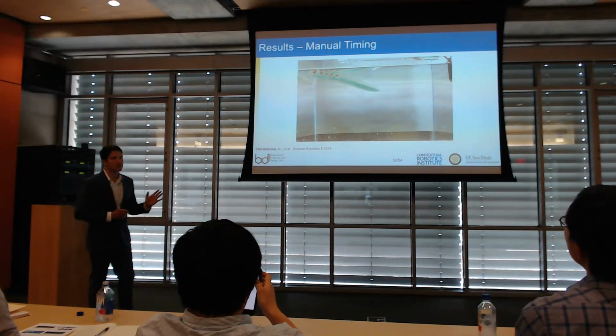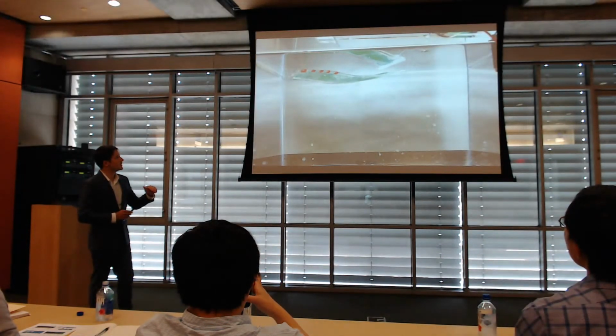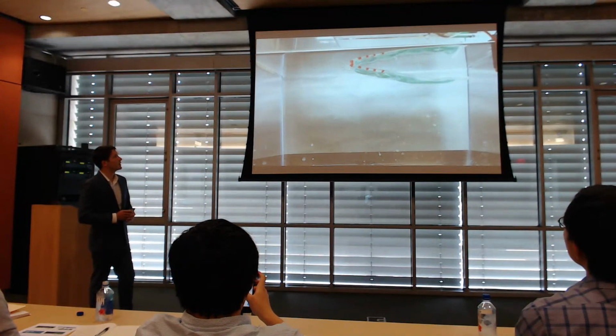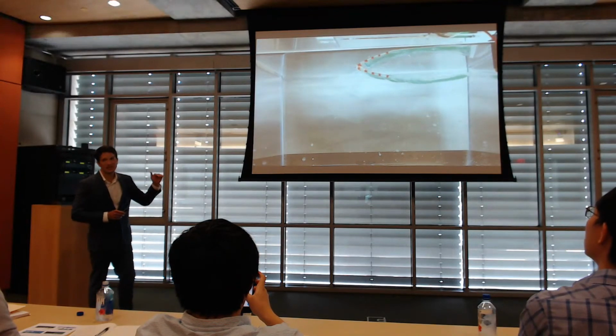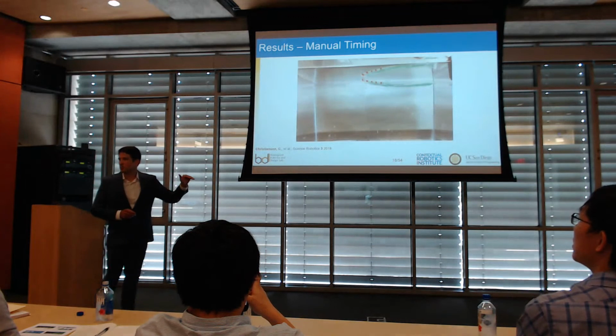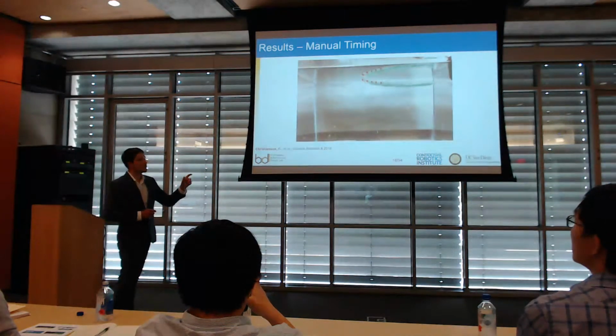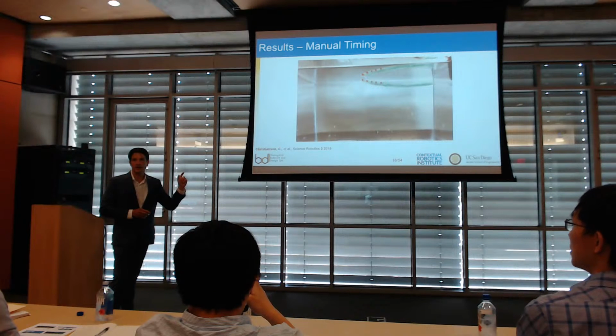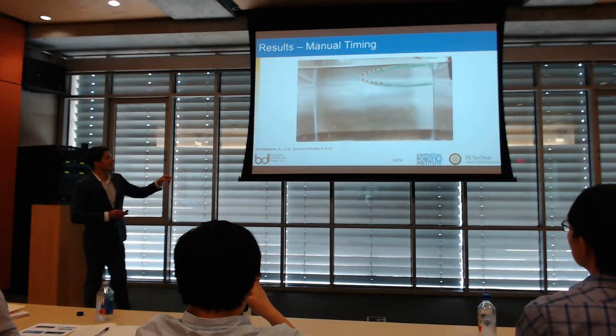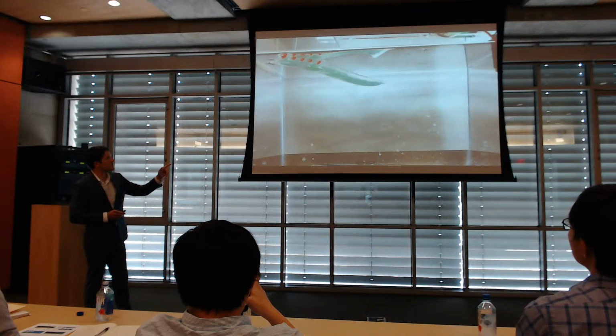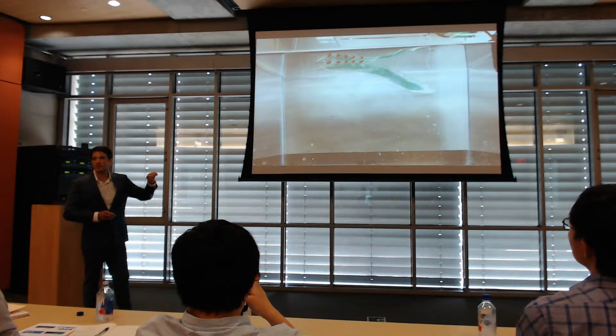Then we also wanted to see if we could get this to swim through the water. This is tethered swimming, just a single bimorph actuator. I'm applying voltage to both sides of the actuator to get it to wiggle its way through the water. The trouble with this one is that in order to get an asymmetry, in order to get it to swim forward, we needed to make part of the actuator more rigid than the other part. So we put a zip tie on the front of it to provide some asymmetry, and also it mostly swims when it can kick off the surface. So it's kind of like an inverted water strider. So that works.